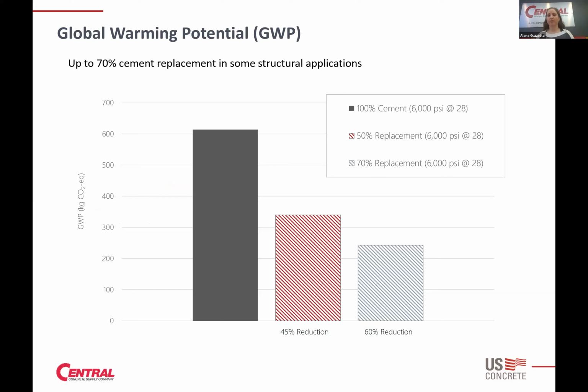And so in an example of how the embodied carbon can be reduced with these types of products, this is an example where we've got 100% cement mix that achieves 6,000 PSI at 28 days. In this particular one, it has a GWP of just over 600. And then when we took a 50% cement replacement mix that achieved the same strength, you can see there's a 45% reduction in the GWP. And then with a 70% replacement of cement at the same strength, we were able to achieve a 60% reduction. And these are mixes that we're able to use out on the market in the San Francisco Bay Area, also in our East Coast operations as well, that we're able to use today.